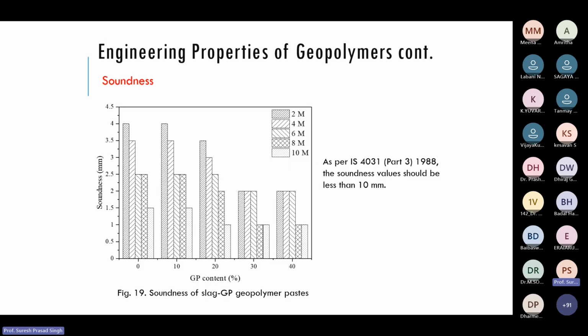Then we have the soundness. Soundness is determined with the different molarities and with GP content. As per IS 4031, the soundness should be less than 10 mm, but we got a maximum of 4 mm soundness.